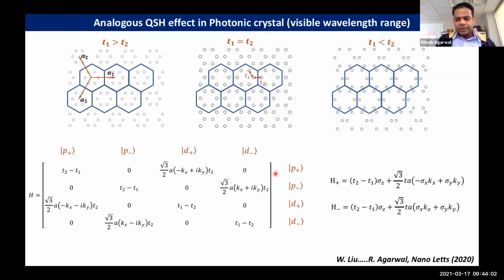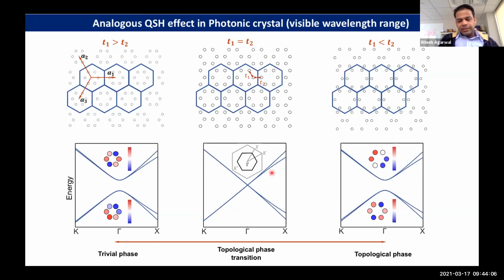Okay, so this is pretty much the idea. An important thing to note here is, as I said, these are all tight binding calculations of the photonic structure. So when you have the regular T1 equal to T2 honeycomb lattice with C6 and C3 symmetries, you have this Dirac dispersion. But if you have T1 greater than T2, then you have a conventional photonic insulator. And as you can see, this quote unquote valence band has a dipolar p orbital structure, and the conduction band has the d orbital type structure. In the opposite regime, when you expand the lattice, it's reversed. So now you have a p type orbital structure in the conduction band and the d type in the valence band. So these two are inverted compared to each other.